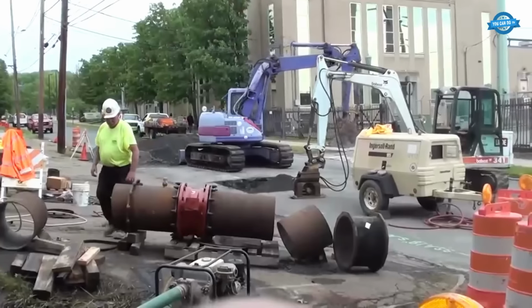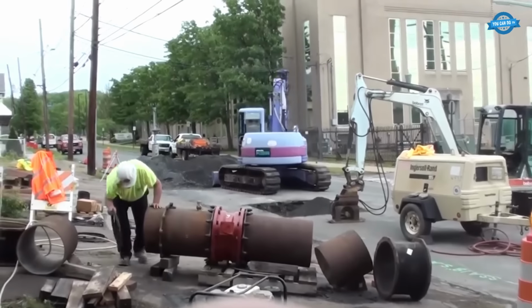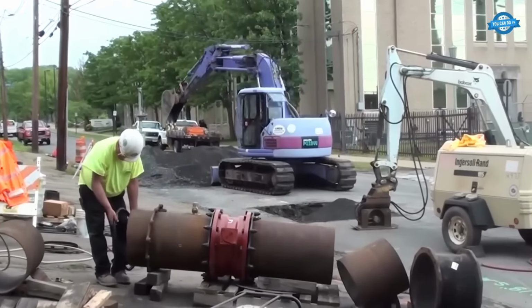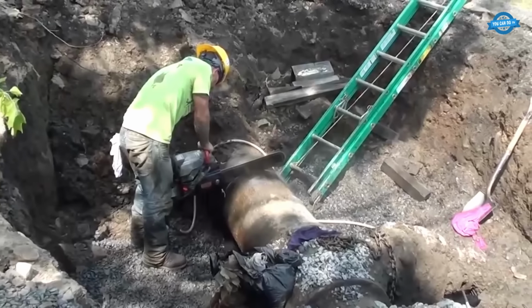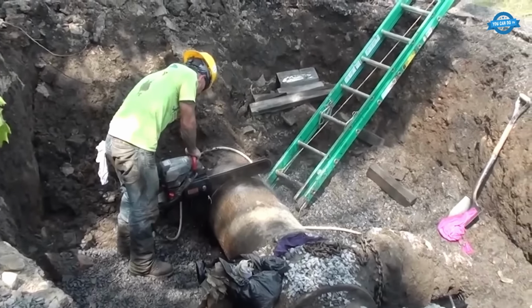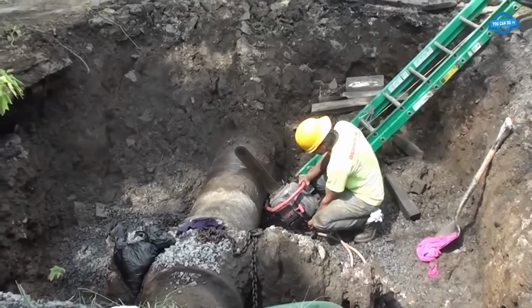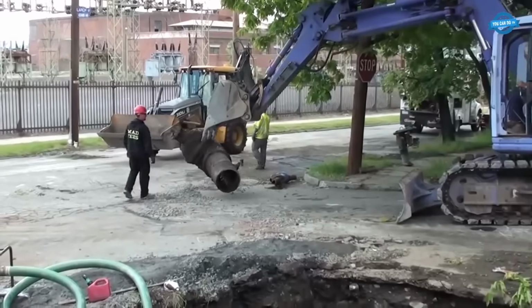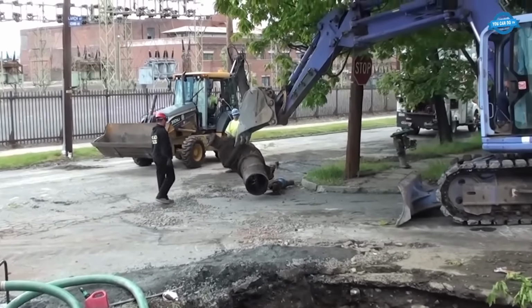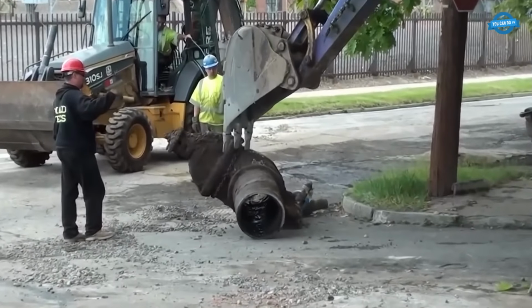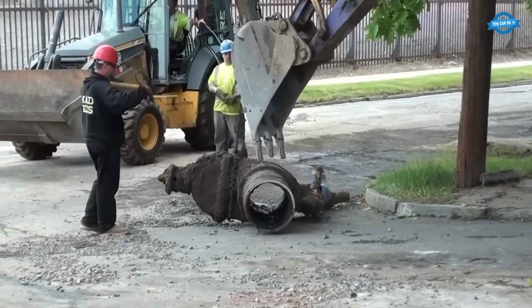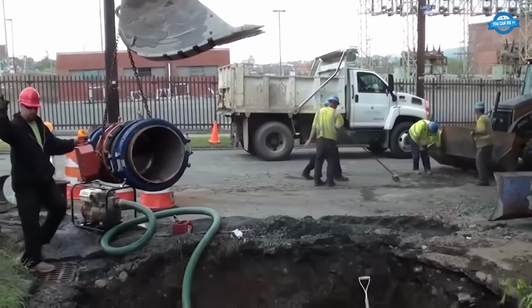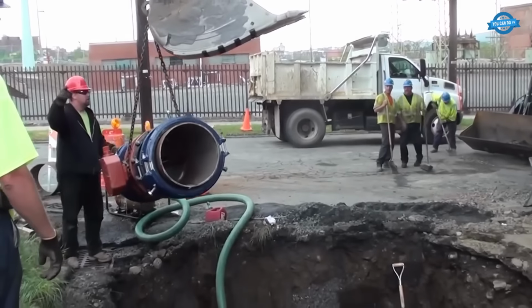Some underground work is planned years in advance. Some begins the moment a main fails under a street. A ruptured 18-inch cast iron water main was isolated using 3-line stoppers. The failed section was cut out with a chainsaw rigged to spray cooling water, and a replacement piece was lowered in and bolted using couplings. Every customer above ground stayed in service throughout.